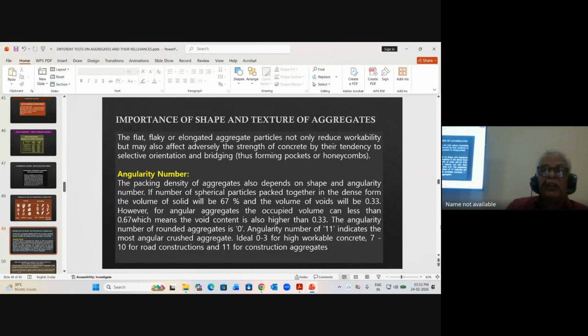Angularity number plays a very important role, especially in road work and construction. The packing density of aggregate also depends on shape and angularity number. If a number of spherical particles are packed together in a space, the volume of solid will be such that if you take only rounded aggregates in a container, about 67% is occupied by the aggregate, remaining as voids.